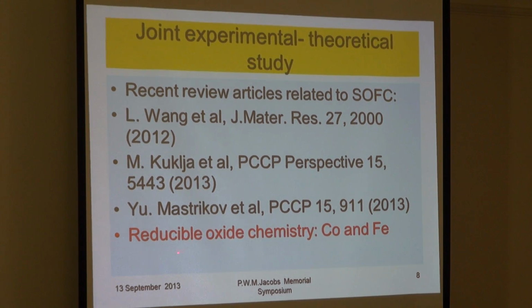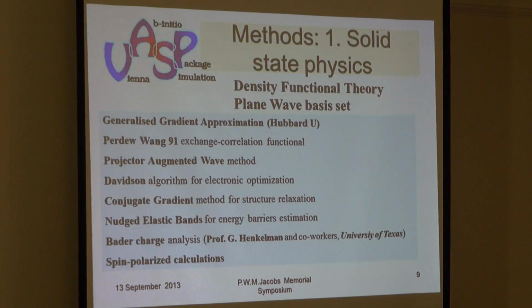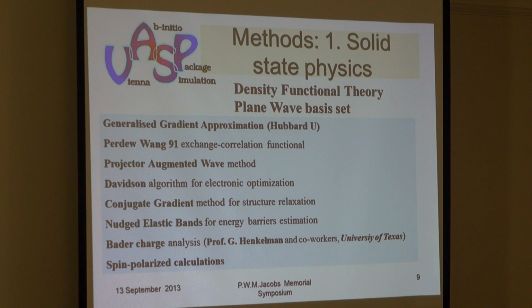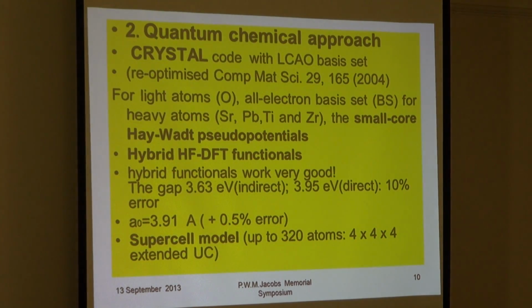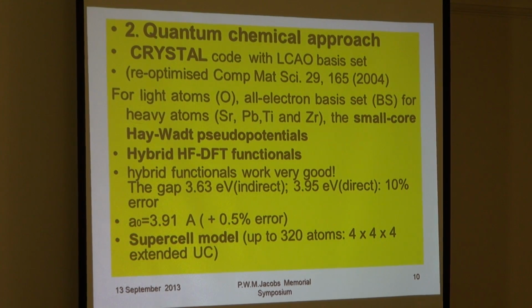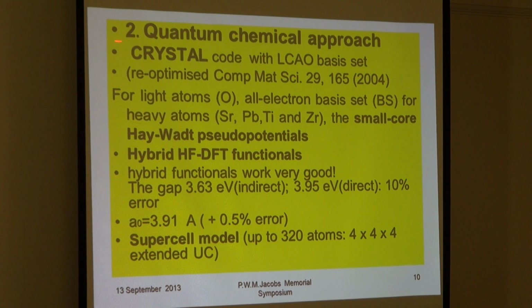But what I would like to stress is reducible oxide chemistry and the properties in these materials. Technically we use absolutely standard computer codes. We use VASP, which is commonly used for density functional calculations in solid state physics. And we use the CRYSTAL code with an atomic basis set. And we also studied these calculations of perovskites with Patrick. When I came to him, we first used interatomic codes, Cascade and GULP, very successfully. And then during my visit we started quantum chemical calculations of perovskites, which we continue now.